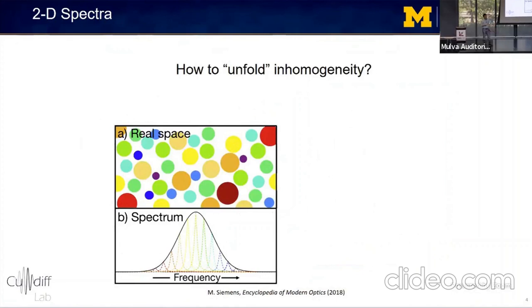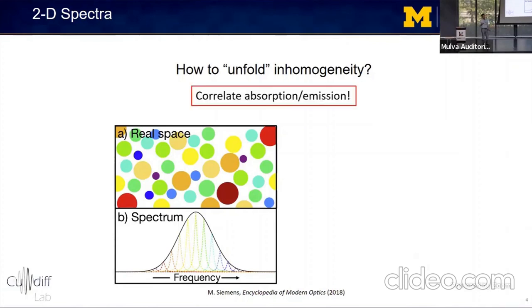So this is the situation I described on the previous slide, where you have nanocrystals of different sizes, all emitting light at slightly different wavelengths. And we want to know about their ensemble average properties, but their individual spectra all combine to give us this broad and inhomogeneously broadened spectrum. So how do we unfold this inhomogeneous distribution to get at the underlying homogeneous line shapes? So the most powerful way to do this is to correlate absorption and emission spectra. So in other words, if my sample absorbs light at a certain wavelength, what wavelengths does it emit at?